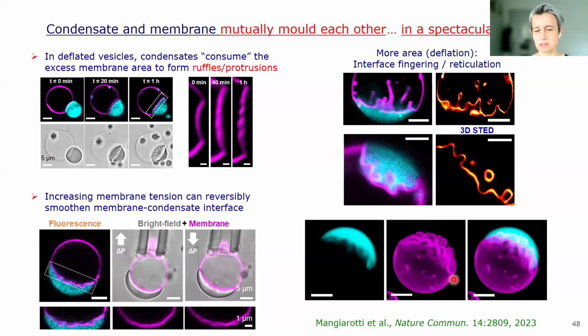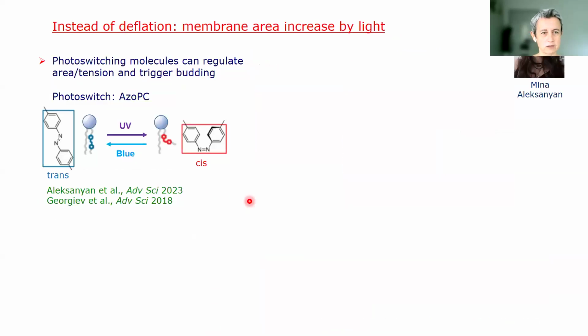And this is an interesting picture here showing that the flat part of the membrane, so this is basically flat on molecular level, coexists with a very wiggled surface or protrusions on the other side of the vesicle. If you apply some tension on the bare part of the membrane, you can pull these wiggles out, and the ruffles would reform if you release the tension.